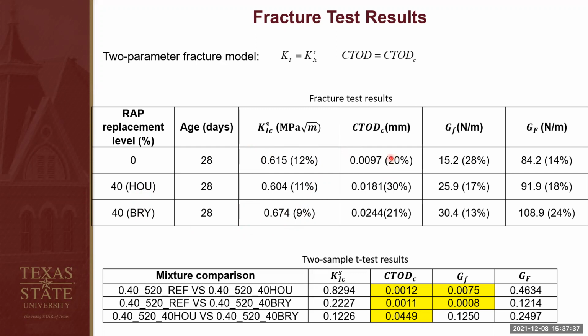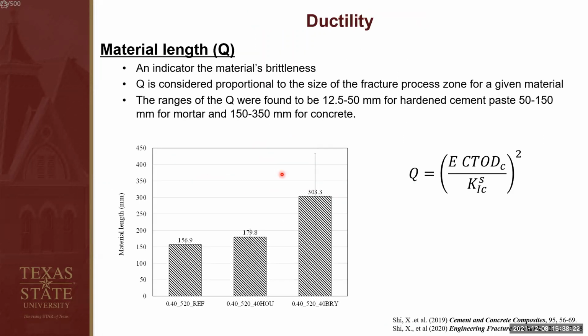For the critical crack tip opening displacement, as you can see, adding RAP would significantly increase the critical crack tip opening displacement. And for the fracture energy terms, which are G_f and G_F, as you can see, adding RAP also improves the fracture energy terms. So even though adding RAP could reduce strength, we found the fracture properties can be improved or can be equivalent to the control specimen. By using those fracture properties, we can also evaluate the ductility of the material. So here I'm introducing a concept which is a material length. It is an indicator of the material's brittleness or ductility.